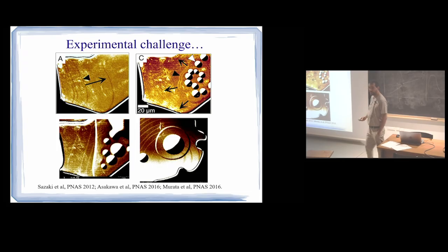We're concerned about this surface, because these authors are observing terraces. And terraces are typical of surfaces which are rather ordered. And the canonical model of growth from an ordered surface is you have a flat surface, you grow steps somehow. This is an activated process. And then molecules come here, and here, and here. So the steps spread horizontally. That's what the authors are seeing.